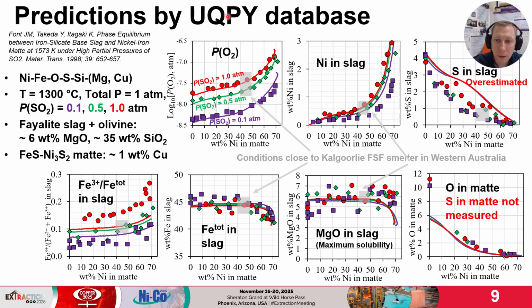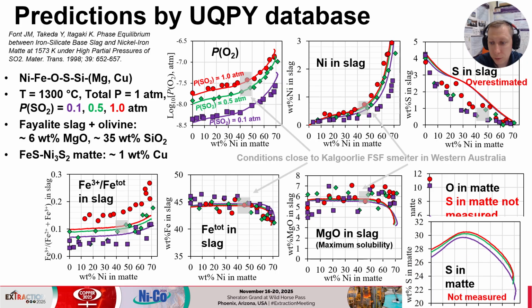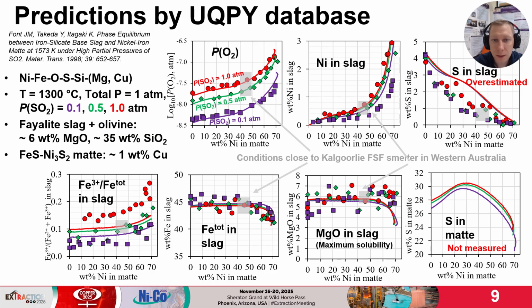Next to the diagrams, we demonstrate the maximum iron concentration and MgO concentration in saturation with olivine. They are reasonably well described. Our model for matte also considers the solubility for oxygen, which is reasonably well described. The concentration of sulfur in matte is an important parameter, but unfortunately was not provided in this experimental study.